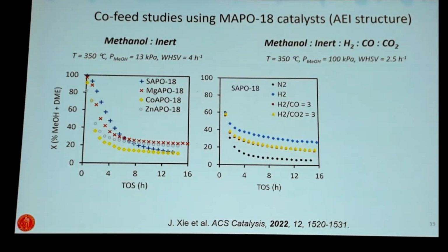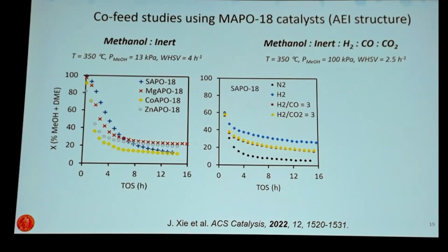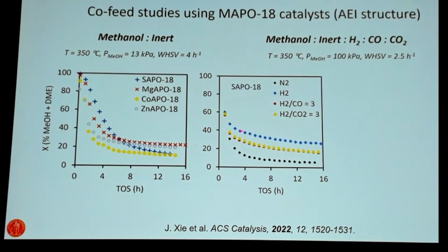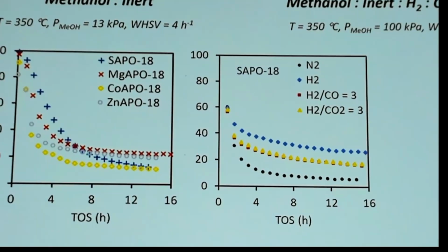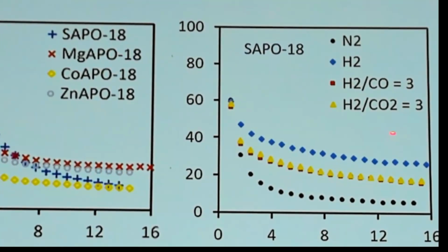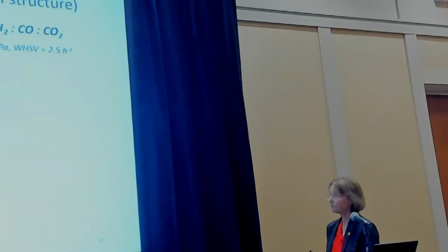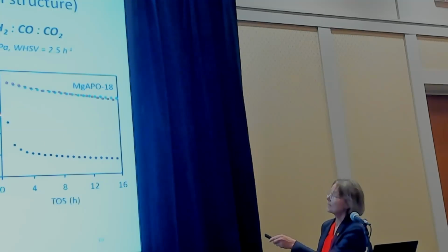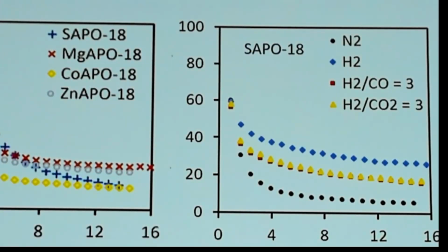So the first thing we did with this material was that we subjected it to co-feed studies. In the first one, we have methanol with nitrogen over the SAPO, and we see the expected deactivation there in black. When we now add high pressure hydrogen, we see much more stable operation, but still deactivation, as we know from earlier work. And then if we co-feed CO or CO2 together with hydrogen, we have an intermediate situation. Doing the same thing for the magnesium version, we see that the additional hydrogen and also the hydrogen with CO and CO2 mixtures give a very stable operation.